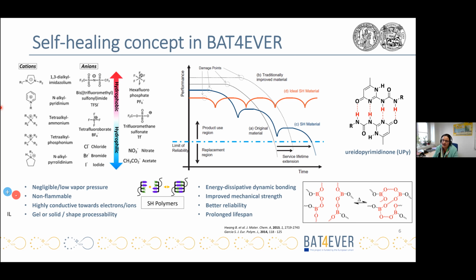Depending on, I think that a good working self-healing polymer can increase the stability of the SEI layer, because it gives a distinct elasticity, so that it wouldn't be broken at the beginning, how to say. So I think that it can have a pretty good influence on the SEI layer.